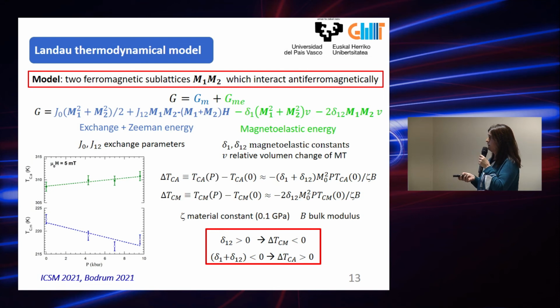Taking into account this Landau theory, we can model this change in the Curie temperature in both the martensitic and austenitic phase. And in this model, we take into account these two different magnetoelastic constants that, in order to fit the experimental data, must have a difference in this case. The elastic constant related to both sublattices must be positive, and the sum of both must be negative too. And in this way, the theory gives us the correct behavior of our system.